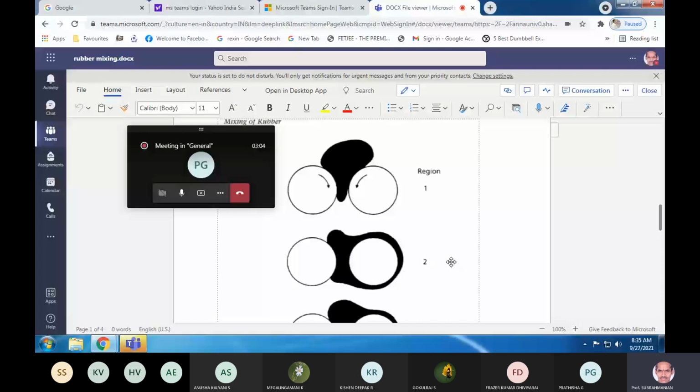So during the course of mixing, they melt and get into the rubber. Stearic acid, for example, at room temperature is solid. The moment it is added to the rubber, because of the shearing of a macromolecule, considerable heat is generated, and that is responsible for melting most of the powdery additives.